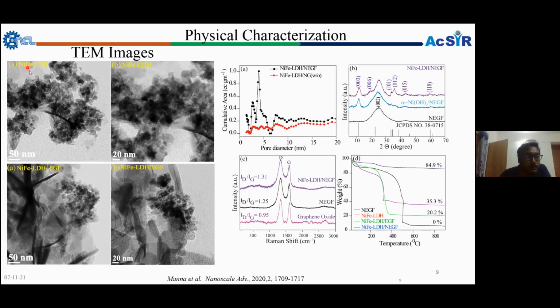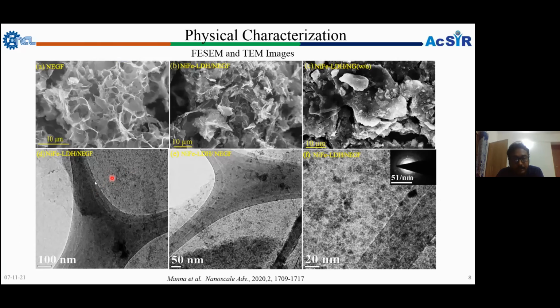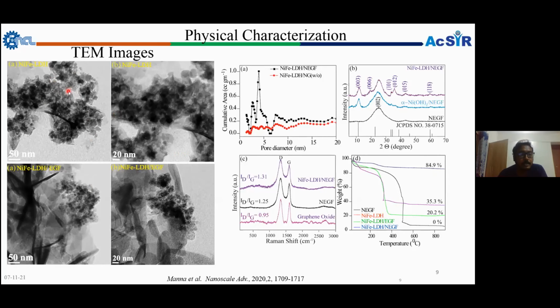So here you can see, without any substrate, the nickel iron layer double hydroxide particle size, how small it is. But in the absence of any substrate like the 3D carbon we used, the particles self-assemble and a big particle size is formed. Another important factor is that without nitrogen doping over the graphene, the layer double hydroxide distribution is not homogeneous. In one place it assembles and forms an agglomerate structure of the nickel iron layer double hydroxide.